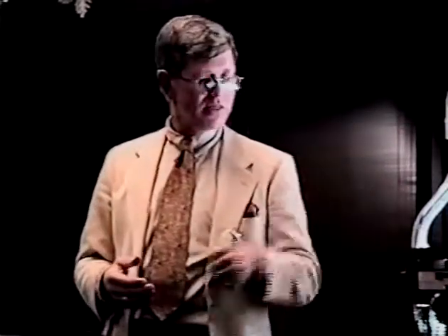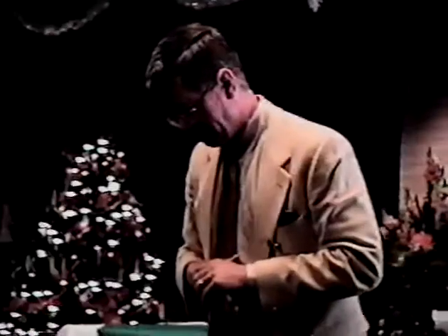And it has a distinct advantage over X-ray photoelectron spectroscopy, because that is limited to the outer few tens of angstroms of the particles because of the escape depth of electrons. So I really can't average over all the particles in the zeolite. Here, this doesn't rely on escape of electrons. The X-rays are very penetrating, so I can measure the binding energy averaged over all particles in the system. So that ought to be a better measure for binding energy for this purpose than XPS.